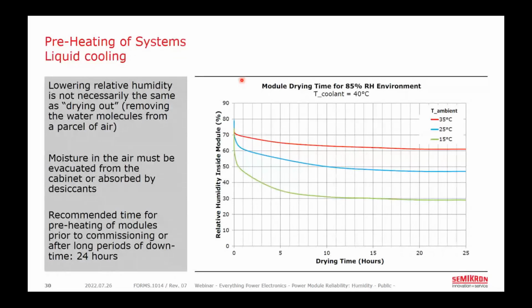And in these cases, the humidity inside the power module can actually be reduced by applying some coolant warmer than the surrounding environment. So here, what we're showing is we're applying 40 degrees Celsius coolant, and these curves are given for 3 different ambient air temperatures, 35, 25, and 15, all starting at 85% relative humidity. And you can see how the relative humidity inside the module changes with time as you're running this 40 degrees C coolant. So on the left, you can see that the humidity drops quite rapidly since the temperature of the heatsink increases quickly in a liquid-cooled system.